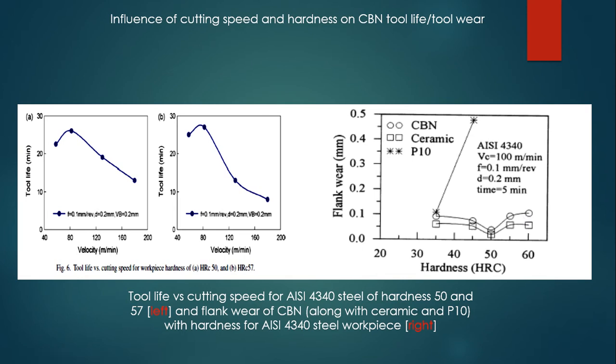There is a high shear stress and strain on the sawtooth chip that causes the high increase in cutting force, and all of these contribute to high tool wear.